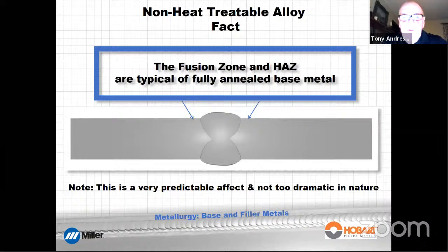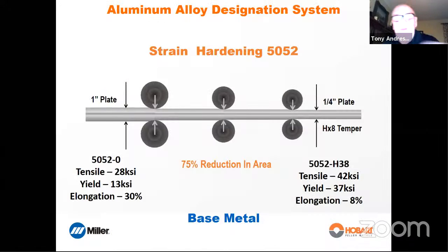All right, so let's go back. What we've actually done here is we have taken the grain structure of the material and we have compressed it and elongated the grains, and we've also added residual stress to the internal structure of the plate because of this deformation. And this results in this increase in strength, right? So now we've got preferential grain structure, we've got internal stress within the material, all of which lends itself to increasing the strength.